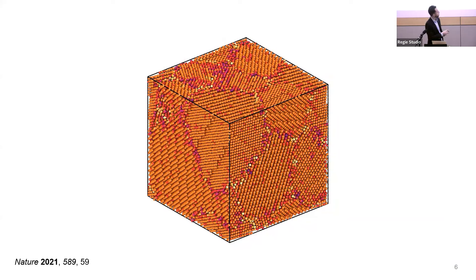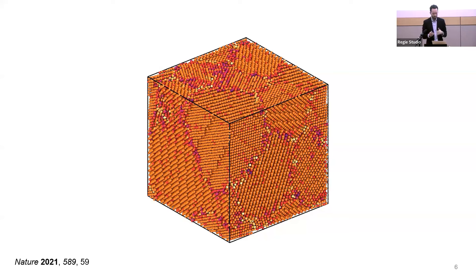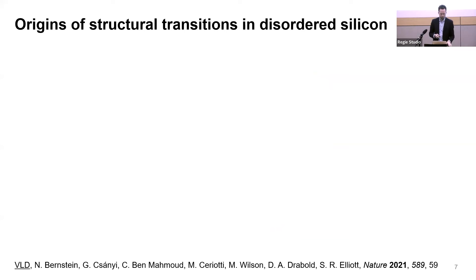If you look closely, you can see a hexagonal close packing of atoms. For those who studied chemistry, this is 2D hexagonal close packing. If you stack it A, A, A — stacking the same type on top of each other — you get something called a simple hexagonal crystal. That is exactly what people have found experimentally at silicon-V, one of the high-pressure forms. We were quite excited to see not just the collapse but also the crystallization, which you can't do with established empirical simulation tools.